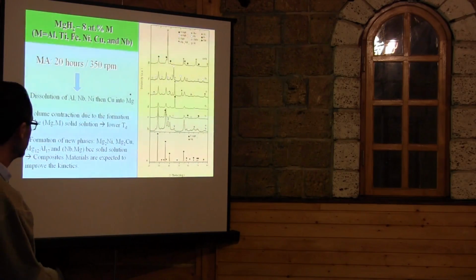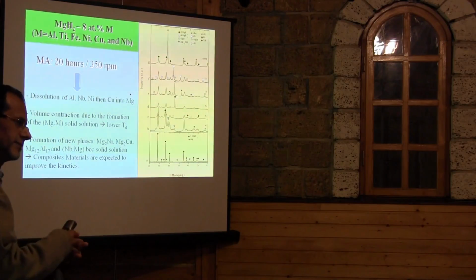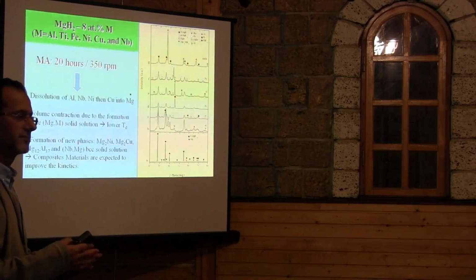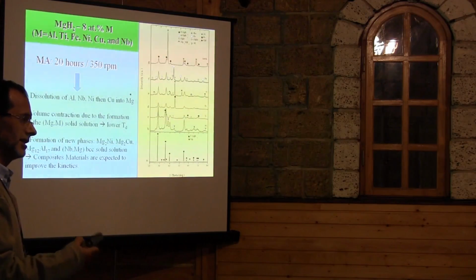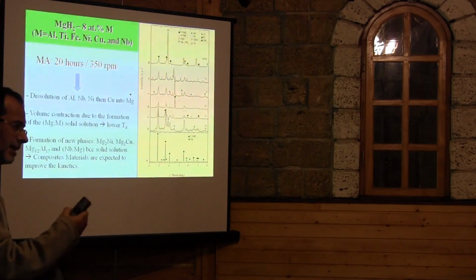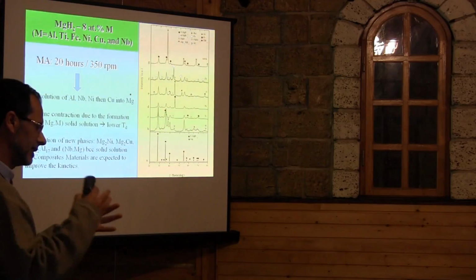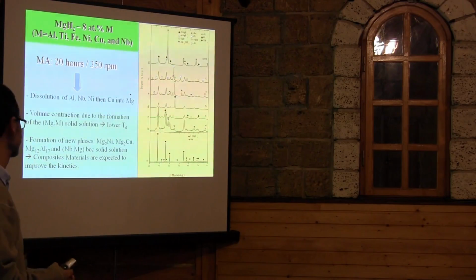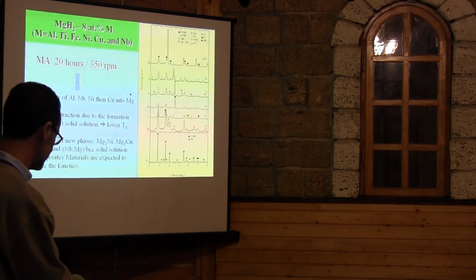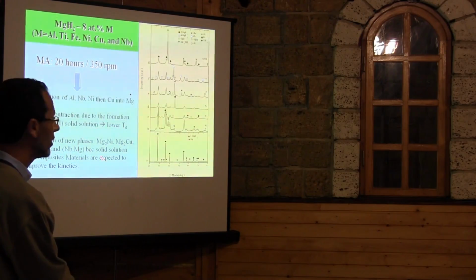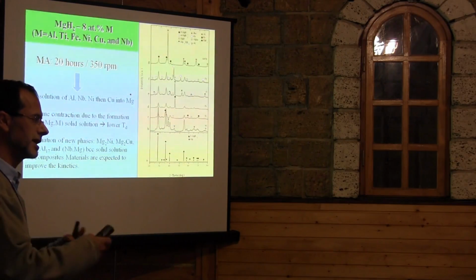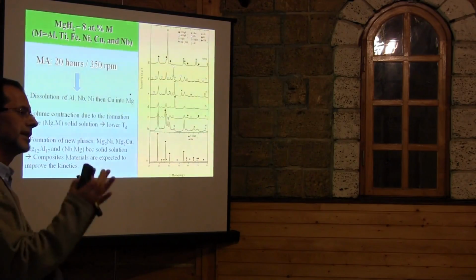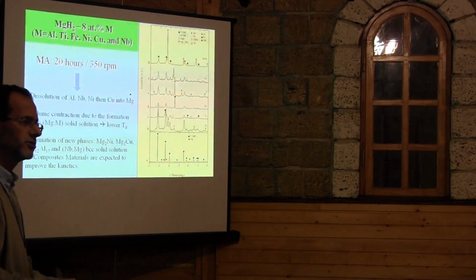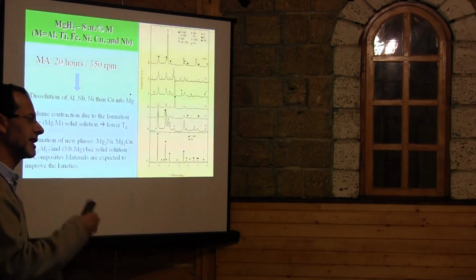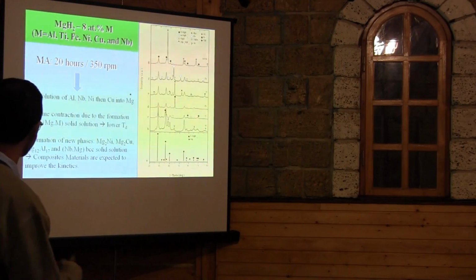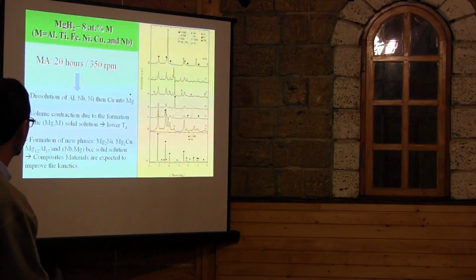At the end, some elements dissolve. Why? Because of the atomic radius, some kind of electronegativity. There are many parameters to control the diffusion of elements into the crystal substrate. So we form some solid solutions, and we form a secondary phase. For me, it's good, because I showed before that sometimes a single phase is not good. The formation of a secondary phase is very beneficial for me, because it helps to improve the kinetics.